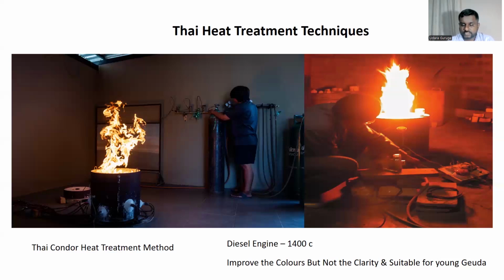The melting point of a sapphire is 2050. So sometimes we have to go even up to 1850. Of course we can go even to 2000, but there's a high chance of the stones bursting because it's too much pressure, too much strain on the stone, so it's not advisable to go over 1850. Usually the rutile needles start dissolving after 1650. So by achieving 1400 Celsius, you will not be able to fully dissolve the rutile needles.